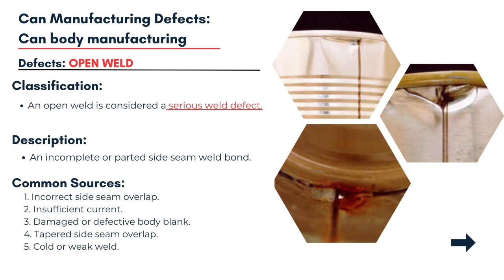Open welds typically result from a variety of manufacturing issues. One of the most common causes is incorrect side seam overlap, where the edges of the can body are not aligned properly before welding. Another frequent source is insufficient current during the welding process, which prevents the metal from fully melting and bonding. Additionally, defects in the body blank material itself, such as damage or inconsistencies, can contribute to weld failure. Tapered side seam overlap, where the overlap varies in thickness, can also cause inconsistent welds. Lastly, cold or weak welds, which result from inadequate heat or improper welding settings, are critical factors in open weld formation. Visually, open welds can appear as gaps, splits, or poorly bonded areas along the seam, as illustrated in the image. These weak points are not only a structural concern but also a hygiene and safety risk, especially in the food and beverage industry.